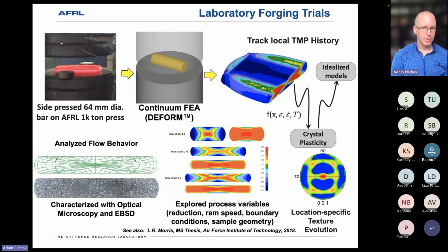So since we were able to successfully reproduce it in the side pressing, we wanted to take a closer look at the thermomechanical history there as a function of location. AFRL has a 1,000 ton forging press, and we did a series of side press operations on 2.5 inch diameter, or 64 millimeter diameter, bar. The aspect ratio, I want to say, was 3 to 1, so 3 times as long as the diameter.